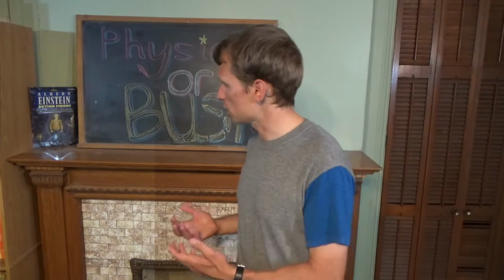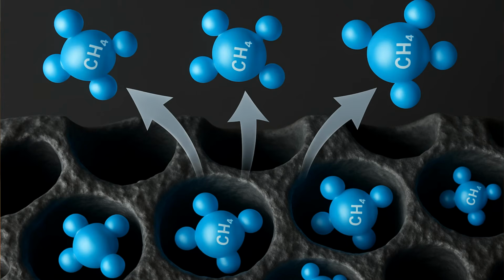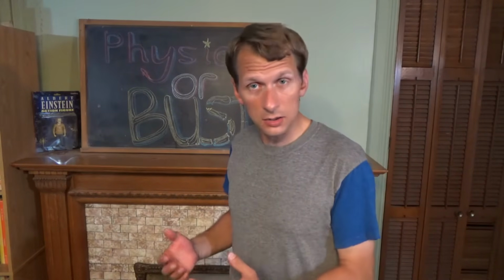It's all about the van der Waals forces. These are weak temporary fluctuations in electron distribution within a molecule, creating temporary dipoles that induce dipoles in nearby molecules, thus making an attraction between the two. It also creates an attraction between the methane molecules and the graphene surface. The nanopores confine the gas molecules, increasing local pressure. Graphene's smooth, highly ordered surface enhances adsorption energy. As a result, methane density in the pores can exceed that of liquid methane at ambient conditions.